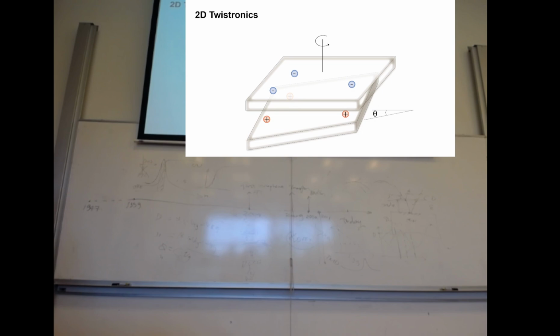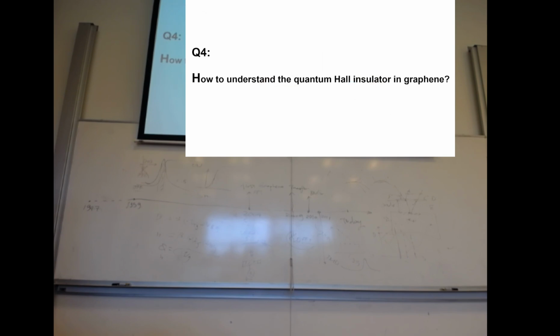And we can also have twisting. If you really want to name a specific point of two-dimensional materials, distinct from 1D, 0D, and 3D, it is that in two dimensions you can have a twist between two surfaces. These two surfaces, because of lattice match or mismatch, will have a new Moiré superlattice, which will modify electronic structures in a way that can never happen in 0D, 1D, or 3D. So this is really something specific to two-dimensional systems.